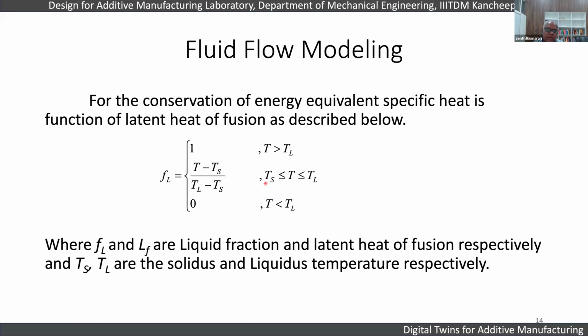A temperature between the solidus and liquidus is a mushy region, and below the solidus is the solid region. So we define the liquid fraction, and use the liquid fraction for the latent heat of fusion. For example, for most of our mechanical properties, especially powder properties, sometimes we use a bulk property, and they may not be accurate. Then we typically use homogenized material properties for 3D printing, or sometimes the bulk density, or sometimes the powder properties.